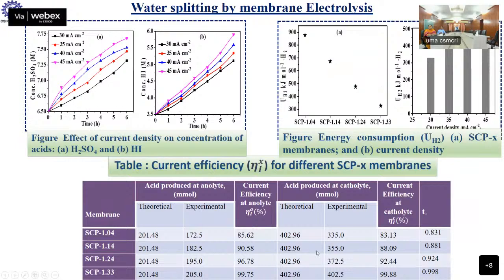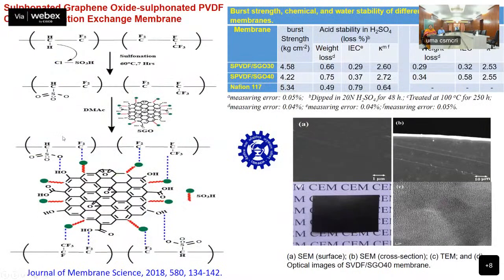You can see the concentration of acid produced at the electrolyte, that is H2SO4, is almost double that of HI in concentration, which should theoretically be 2 times. So it is also supporting our calculation. Another type of membrane has been developed for these water splitting phenomena.